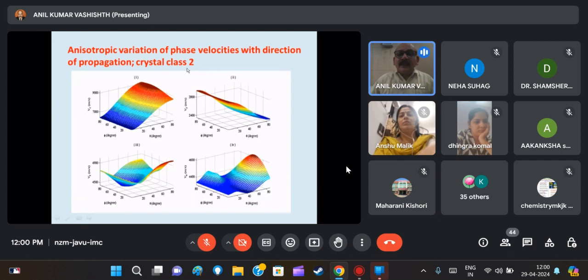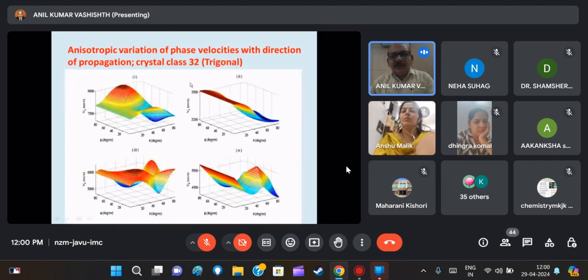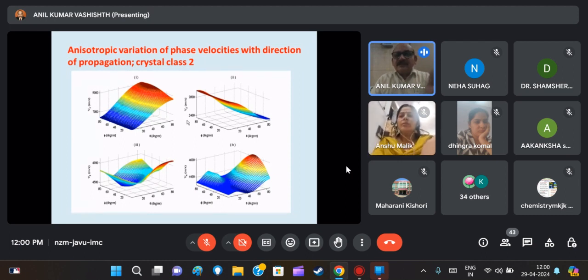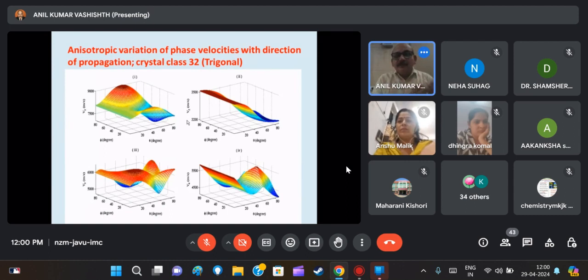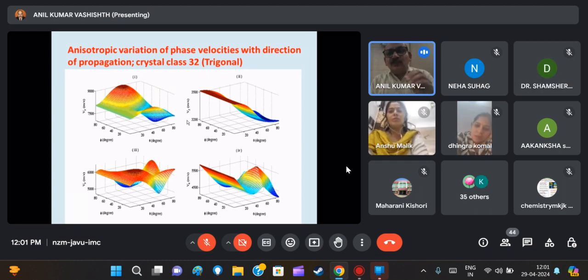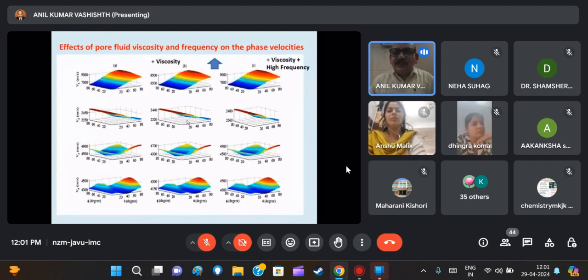Similarly, these are the results for class 2. They are more or less the same. But you see how these results and those results are different just by changing the symmetry, from monoclinic to trigonal class. The result is changed significantly. It means piezoelectric sensors are going to behave differently depending on their elastic orientation. It means we have to be conscious while characterizing the elastic properties of the crystals so formed. Every crystal formed in the lab cannot be treated as 2 mm, or obviously as 6 mm, just because the predecessors have used it.